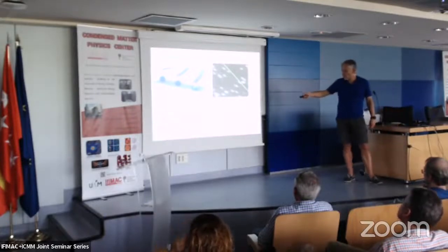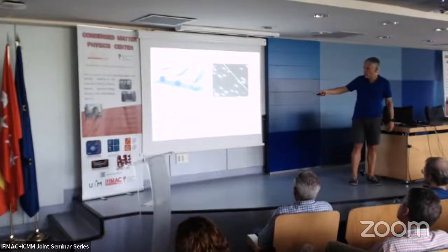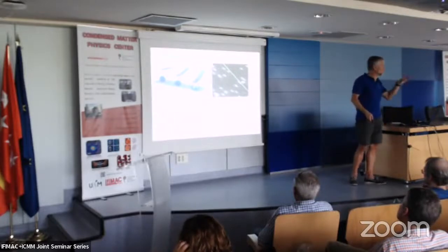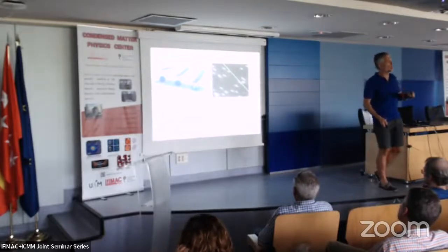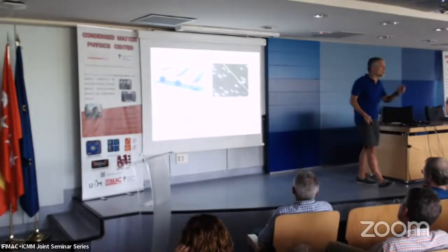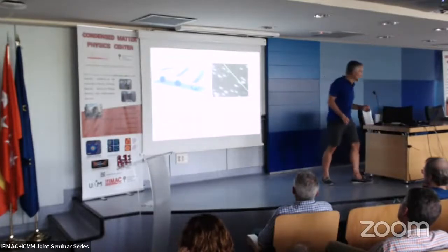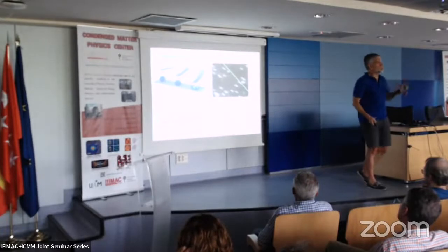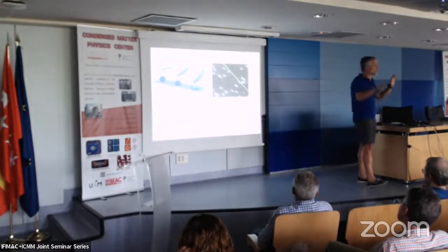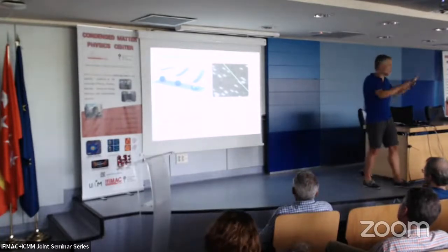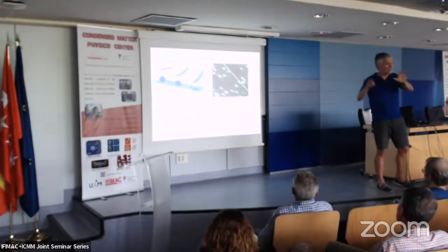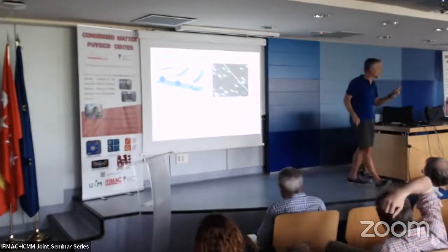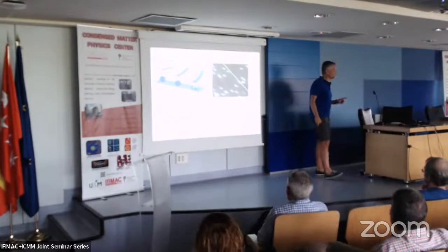in black color, you can see the force curve, and in green color, you can see the light signal. So it's important to remark here that our system is working simultaneously. You can measure fluorescence and atomic force at the same time, because in other systems, the commercial systems, you have to make a correlative measurement. You have to measure first AFM, then switch off AFM, and then measure fluorescence. Here, you can do the two things at the same time. So I think this is important to remark.